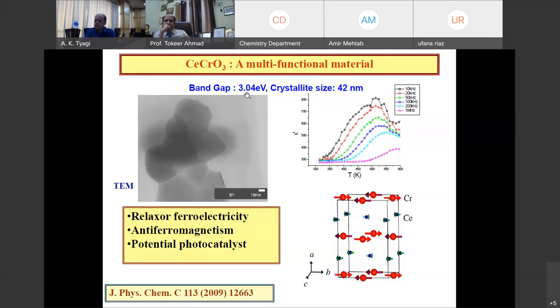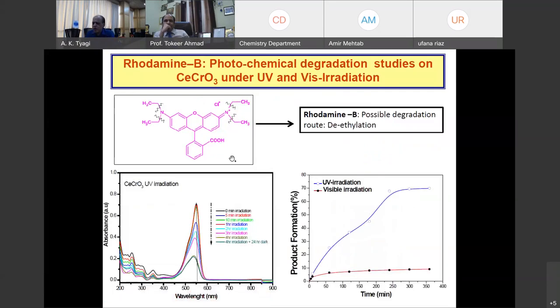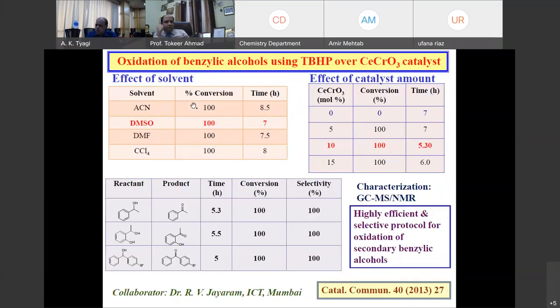So the compound was expected to show photocatalysis also. Not surprising at all, because the compound has a band gap of about 3.04 eV. So we could use this compound for degradation of rhodamine B by photochemical ways. What was more surprising was that this compound could be used as a redox catalyst in organic reactions also.